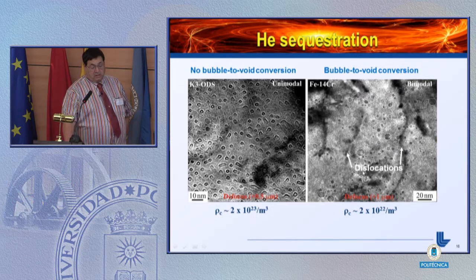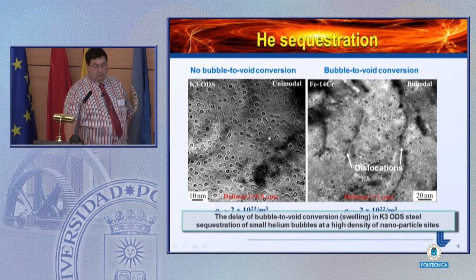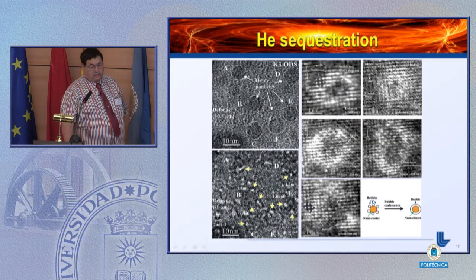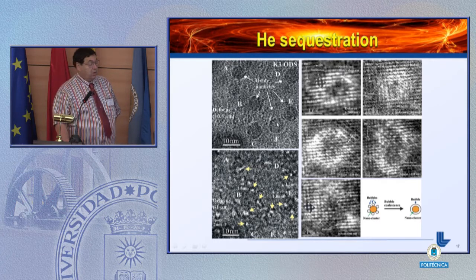Now, if you notice here, the densities of these cavities are shown here. And the density in the case of the ODS, where we are essentially seeing the effect of what I would call a solid state surfactant, is an order of magnitude higher. Yet when we go and count the number of ODS particles, we can't account for the number density of these small cavities. So where are these extra cavities nucleating? And what we discovered was that in addition to the ODS particles that we could see with an electron microscope or with 3D atom probe, there were also particles that only became visible when they became decorated with helium.